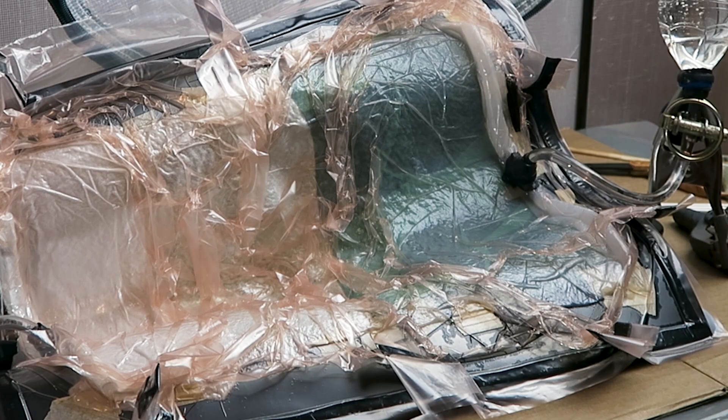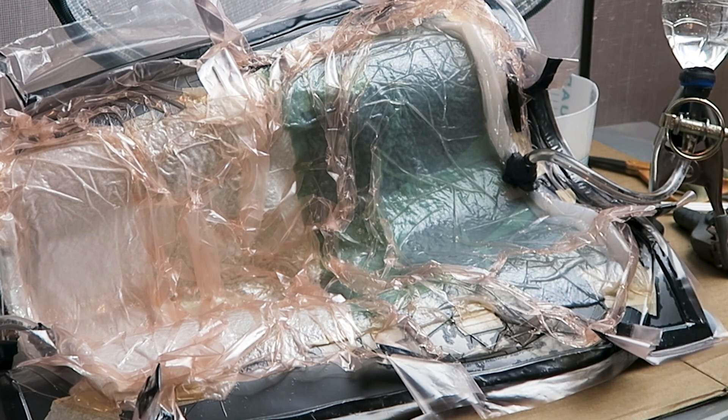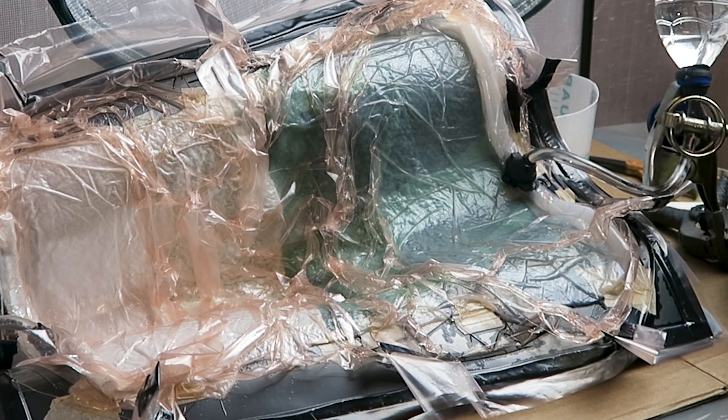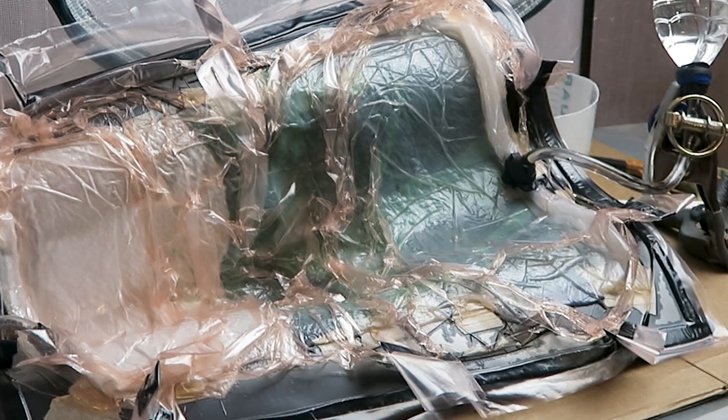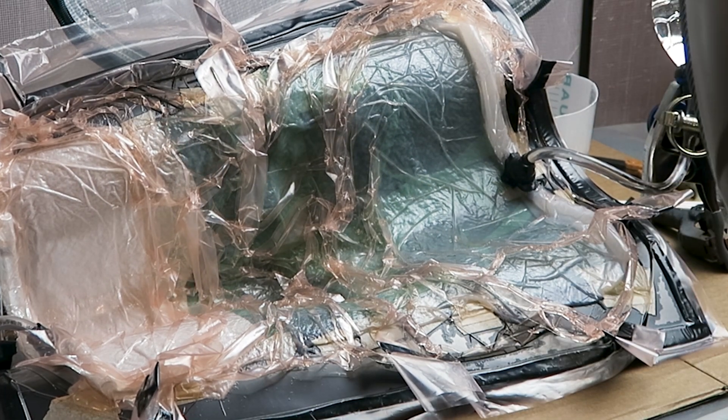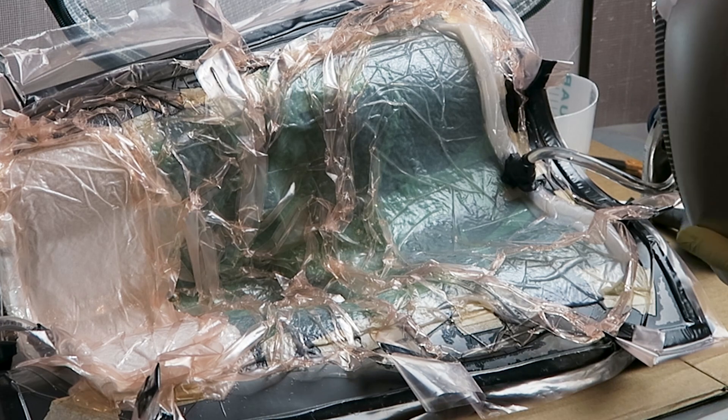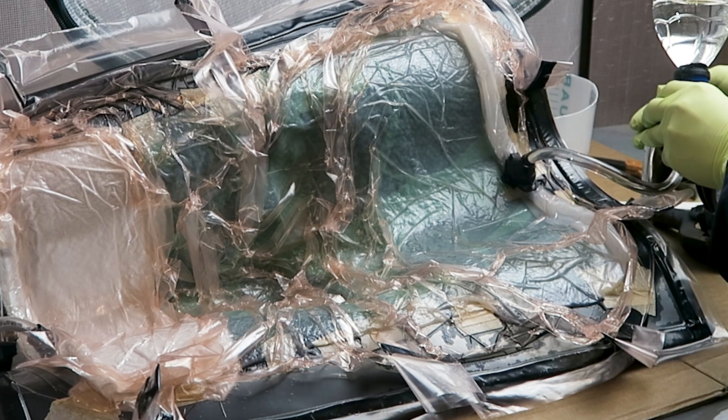The problem came due to this being completed in a very cold garage, so I was using a heater to heat the piece up and some of the tacky tape softened a little bit too much. The plastic pulled away and quite a bit of air got into the mold so it could no longer hold a seal after that. I was unable to find the leak and it was already towards the end of the infusion process.